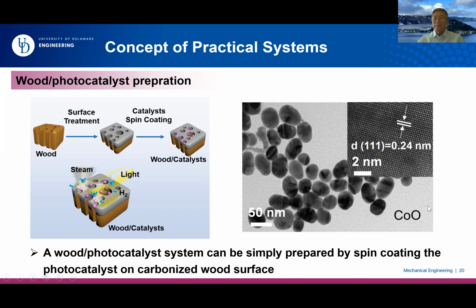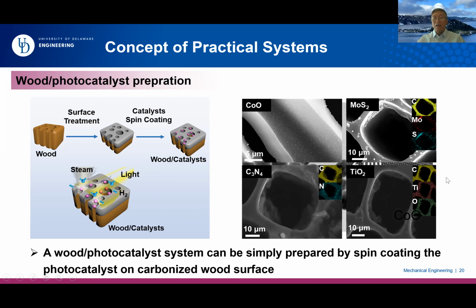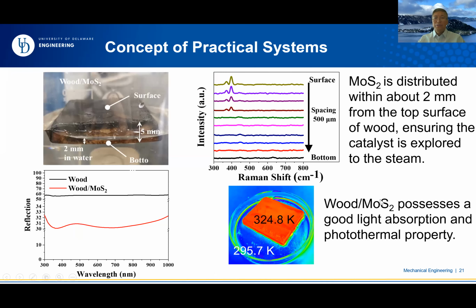So let me show you some examples. We tested cobalt oxide, a typical catalyst for this photocatalytic reaction, with a size of about 15 nanometers in diameter. And not only cobalt oxide, we also tested other catalyst materials as well, like molybdenum sulfide, carbon nitride, and titanium oxide. So let me show you some results.